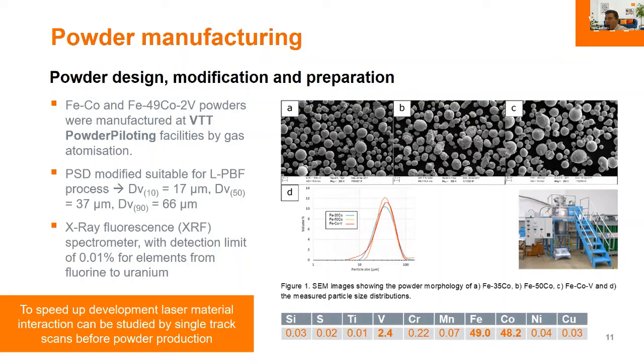Particle morphology is one key issue when we are looking at good flowability of the powder, and typically some kind of modification is needed. So the powder is classified to a certain particle size distribution. In the case of our laser powder bed fusion system, typically it's something like 15 microns to 63 microns that we are looking for. And of course, then the composition: is there homogeneous chemical composition on different sizes of particles, for example? Because if there is some evaporation, then the small particles could have a different composition than the bigger ones.